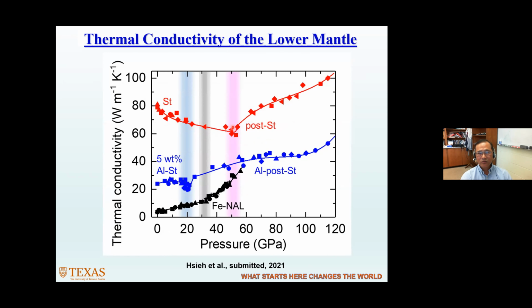The value becomes minimum at the ferroelastic transition and then increases quite significantly in the post-stishovite phase. If you add aluminum impurity of about 5%, the thermal conductivity value decreases by a factor of 2 to 3, but remains relatively high. And for the NAL phase, it undergoes the spin transition, and the low spin state also has high thermal conductivity.